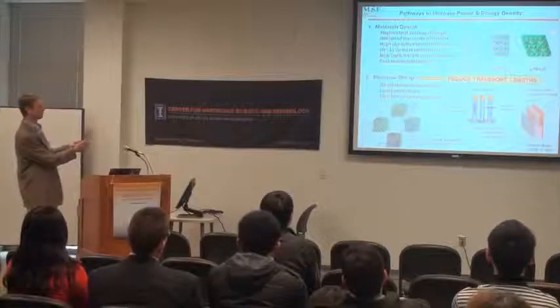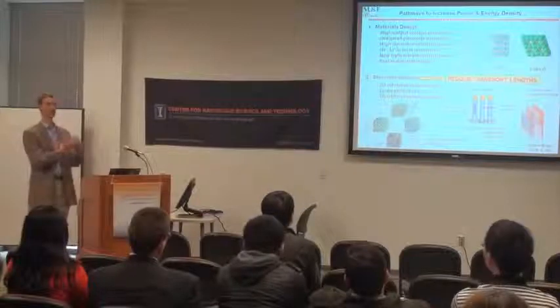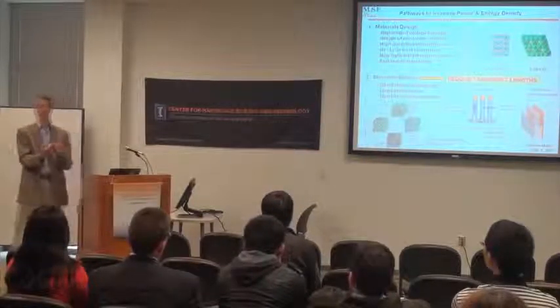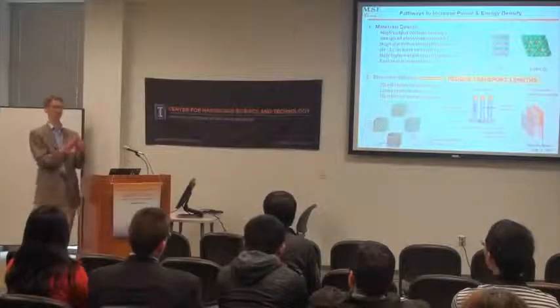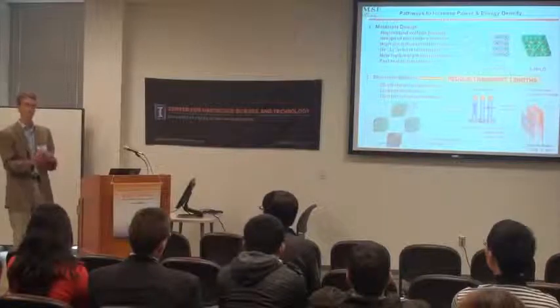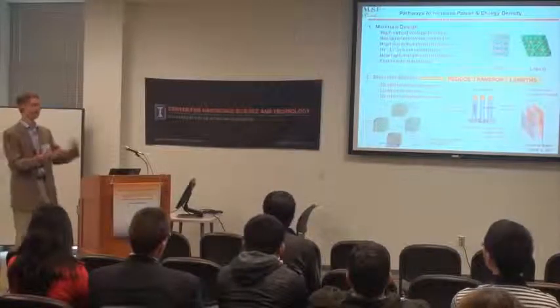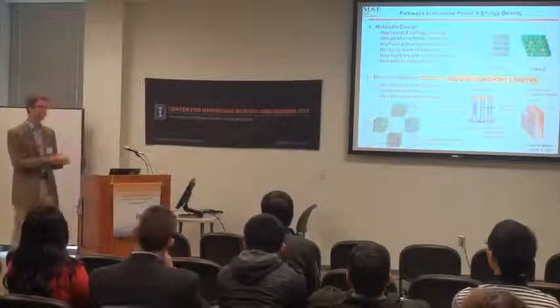So if you're going to increase power and energy, there is a number of new materials that have been developed over the last 10 years, and this has led to incremental, a few percent per year improvements in energy. And so what traditionally was, say, lithium cobalt oxide, you learn to dope this with a little bit of iron, a little bit of aluminum, a little bit of manganese, and each of these steps, which is now 5 to 6 element systems, gives you a little bit more energy density.